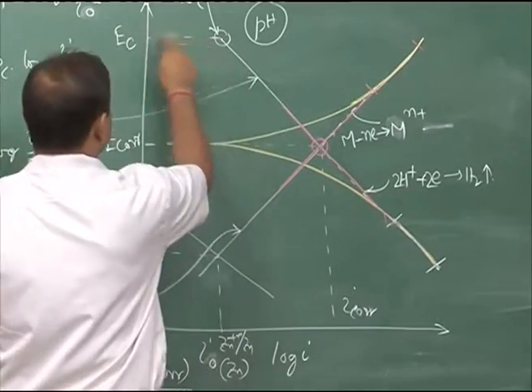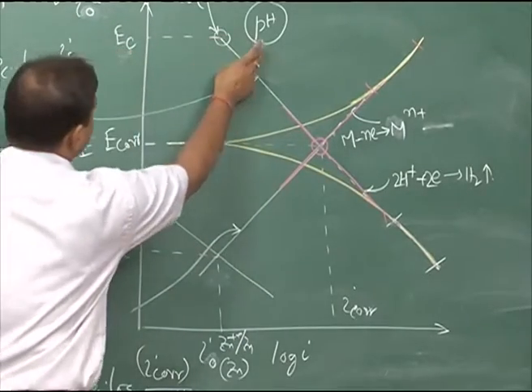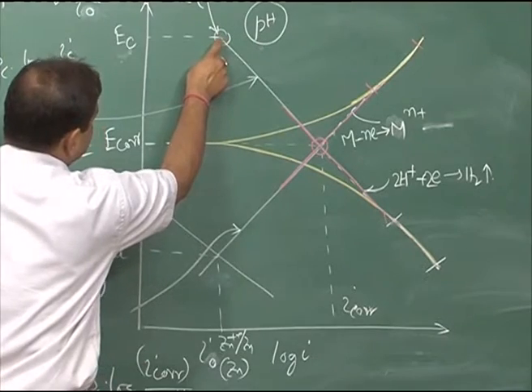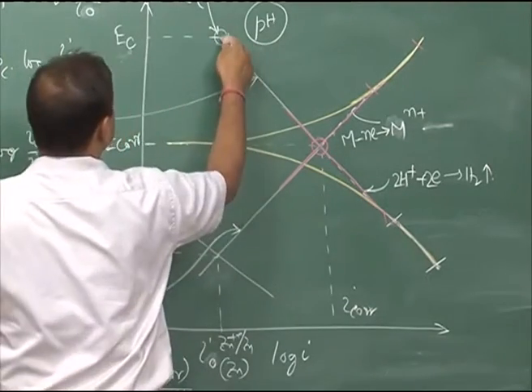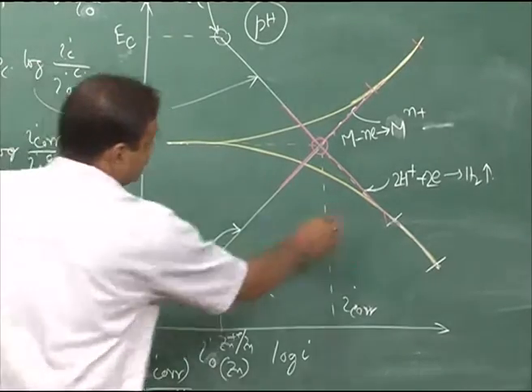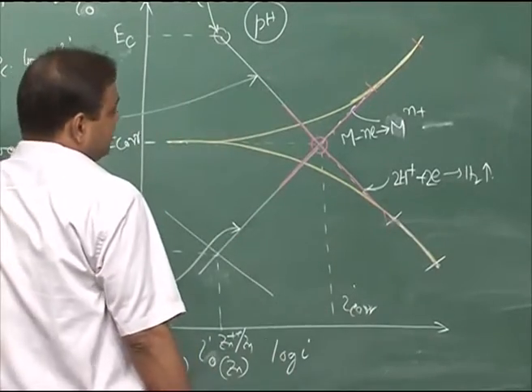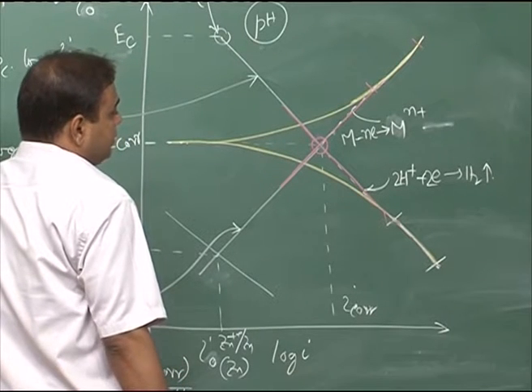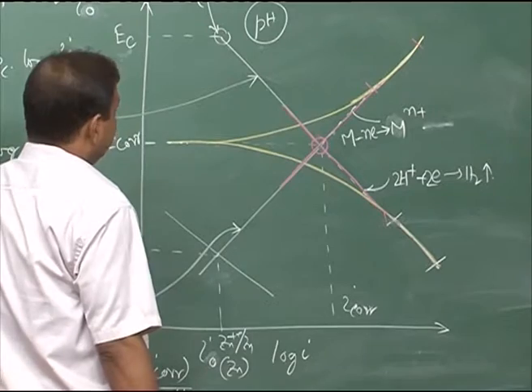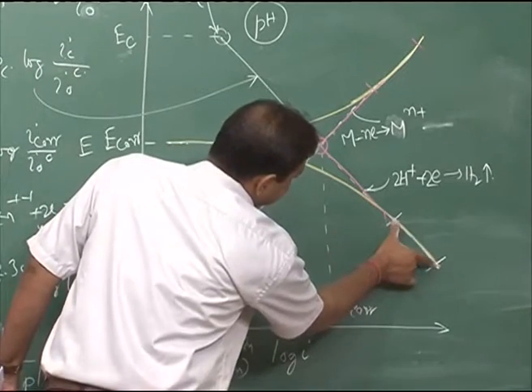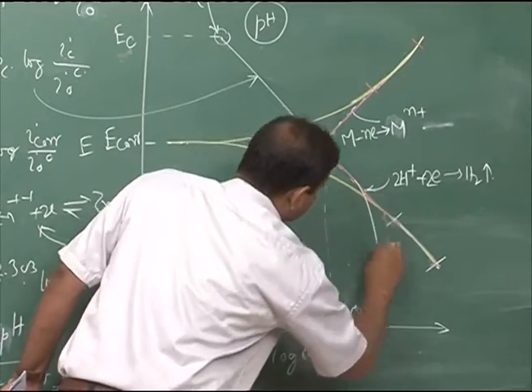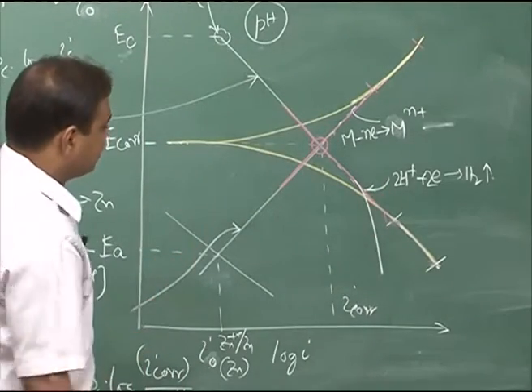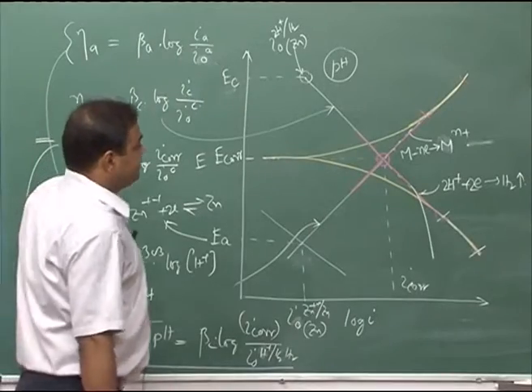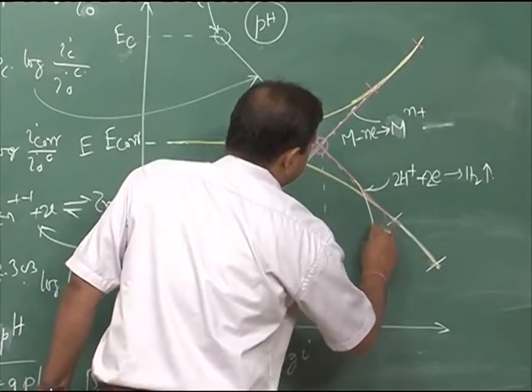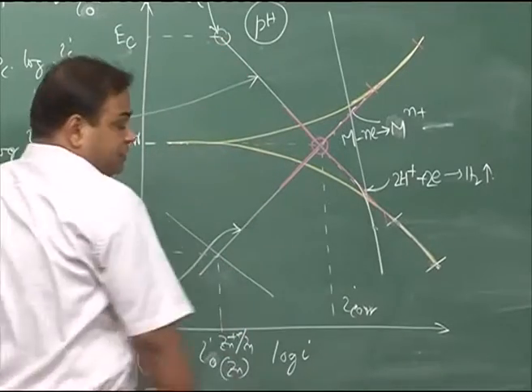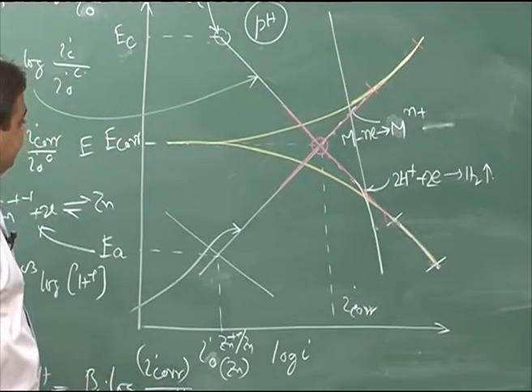Because this Ec we can find out from the pH, it has to be connected and this straight line should pass through this point. But if it is not straight and linear, then we have difficulty, because there could be a possibility of concentration over voltage. So before reaching this linear part, it can bend down and become concentration controlled. In that case, this is the linear part - if we extend it like this, we will not reach this point, so that gives a wrong result.